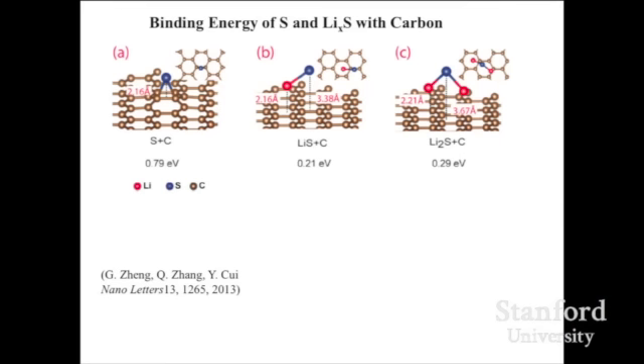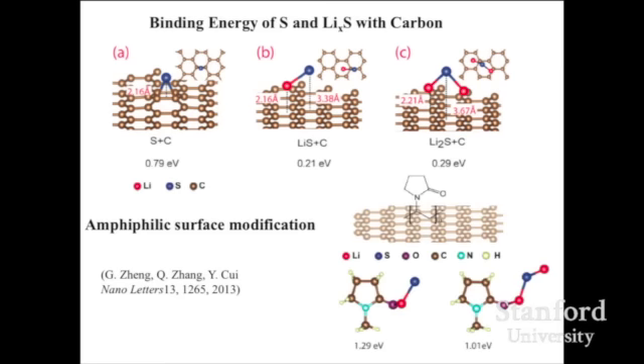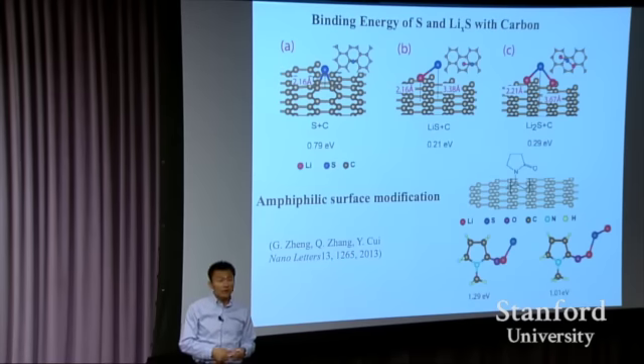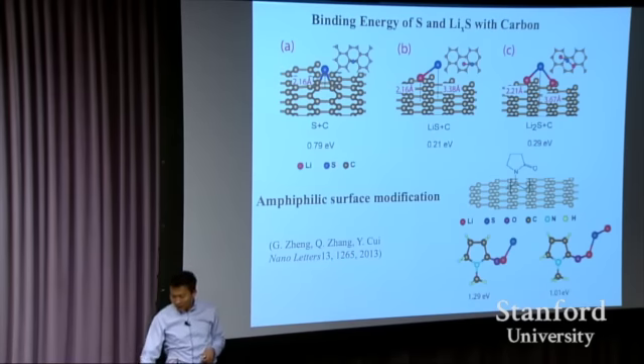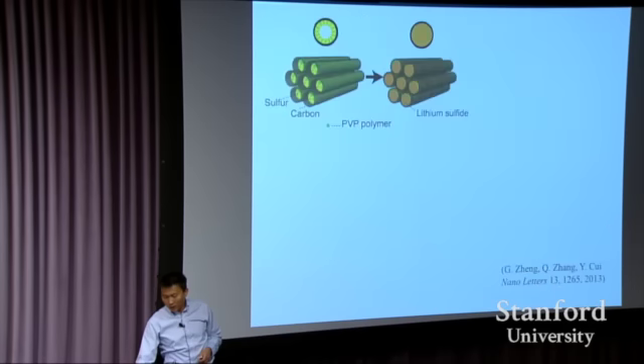So why don't we do this then? We can actually confirm this: sulfur likes carbon, the bonding energy is high, through ab initio simulation. But lithium sulfide, they don't really like it at all. This is confirmed. Then we said, why don't we put in a bifunctional polymer right there? For example, PVP is a polymer having a hydrophobic chain with this polar group right here. This guy must like lithium sulfide. They're all polar. And the surface will like sulfur. So you have both engineered, co-located together, beautiful things in nanotechnology. That's what you can do. This really solved the problem.